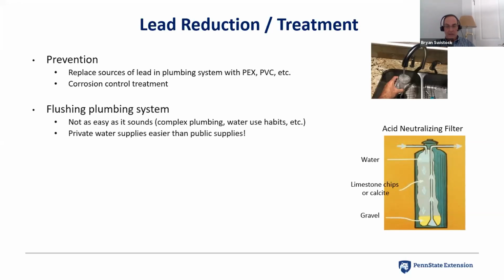The simplest treatment method, and if you want to call it treatment, is simply to flush the plumbing system and get fresh water out of the well, because it does take some period of time for lead to leach from the plumbing. And usually we throw around an hour minimum, sometimes several hours, before lead can reach appreciable concentrations as it sits in contact with that lead solder. So the idea is, if you just go to the tap, run the water and flush out all the plumbing and draw fresh water from your well, that you'll get lower lead concentrations. It assumes that you don't have lead in the source water, which again is a rare problem, but it will work very effectively if corrosion is the main issue. But it's a lot harder than it sounds, really.